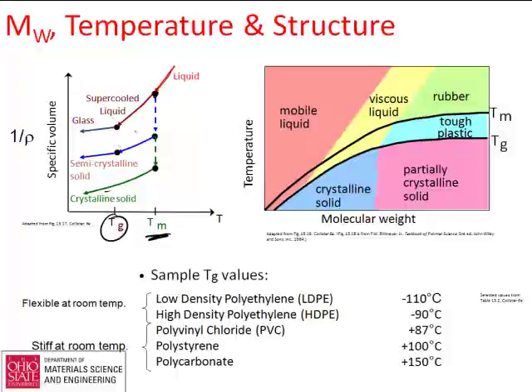So polymers and glasses are things that have hard times solidifying. You hit the melting temperature, but they may not be able to solidify, so they have this amorphous, disordered structure that gets locked in and can become glassy. Get below the glass transition temperature and things get very hard. So polyethylene has very low glass transition temperature, so at room temperature it's still pretty pliable. Some of these other materials like polycarbonate has a high glass transition temperature, so at room temperature it's pretty darn stiff, for example. So that's how we end up varying the properties of polymers with temperature, and we can control